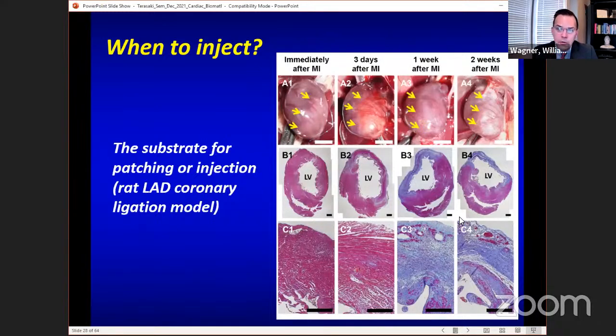We've done a number of studies with different gels and asked some of the questions. One of the questions that we had, we came to after some discussions with one of our cardiology collaborators, and it was this time of intervention. And he really impressed upon me the reticence for the clinician to intervene in that early period. And he said, 2 weeks is great. And I said, well, we'd like to back it up because we think we're going to get more benefit the earlier. He said, well, maybe 3 days, they might entertain that, but it'd have to be much better than 2 weeks. 2 weeks is good. And even later, would be better. So you're doing this trade-off between losing function in the patient and putting the patient at risk for an intervention.